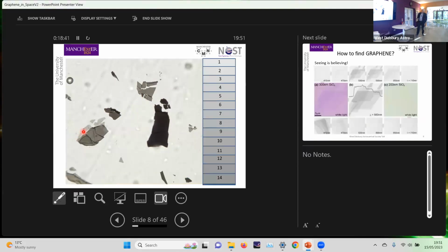Here I've tried to indicate how dark something would be. So if I look at single layer, you wouldn't see it, because it's almost the same as the background. It's identical to the background virtually. So you won't see single layer this way. That's why you have to put it on silicon dioxide, in order to see it. But some of the other layers, like 9, 10, you can definitely see, because some of these are 9, 10 layers thick. So you can actually make what we would call graphenes, but they're multi-layer graphenes. They're not yet graphite, because you have to get to about 20 layers or so before you start seeing the properties of graphite in the material. So these do have different properties from graphite. Unfortunately, the multi-layer ones also have different properties from graphene. So it's a complex business looking at these things.